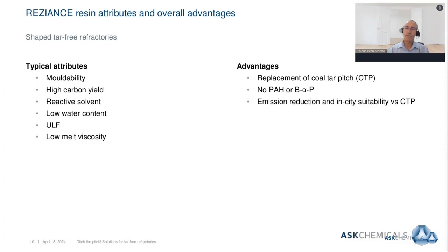The type of attributes when considering to use a phenolic resin in the place of coal tar pitch. Typical attributes brought to the table by phenolic resins could be factors such as moldability, carbon yield. In some cases, like liquid resins, even a reactive solvent can be present. And in our case, we focus heavily on water contents because that relates directly to rejects, such as caused by cracking and lamination. And we also focus heavily on free monomer contents or residual monomer contents. The acronym there, ULF, ultra low free formaldehyde. And of course, we prefer to be below the declarable GHS levels of 0.1%. Another typical attribute could be something like melt viscosity or softening point in the case of solid phenolic resins.